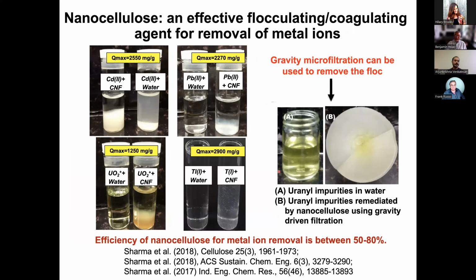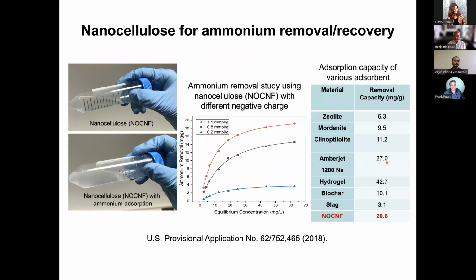And the solid part in the suspension we use as a coagulant. It's negatively charged, so we can remove, for example, all the positively charged contaminants: cadmium, lead, thallium, uranium. And once you remove them, they will coagulate. And then once they coagulate, you can use very low energy microfiltration to remove these materials. So it turned out to be a very efficient way to remove these.